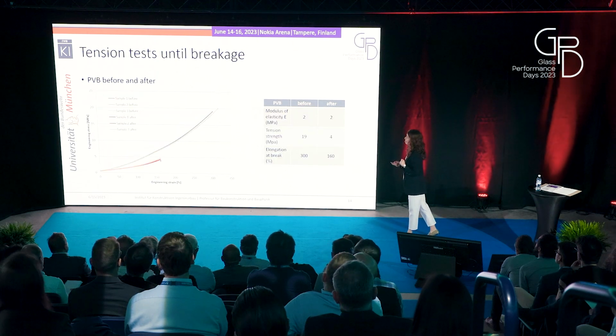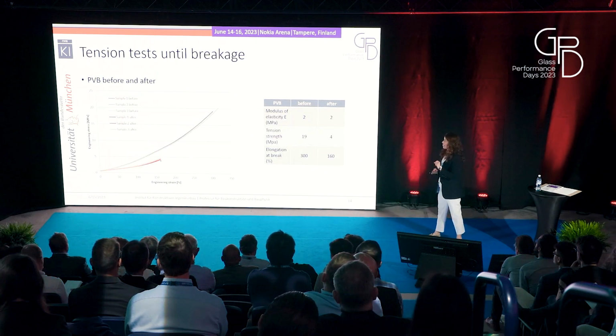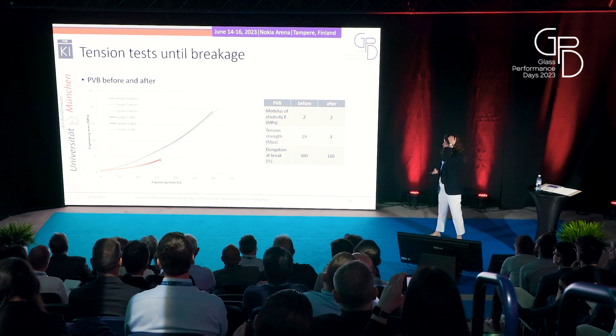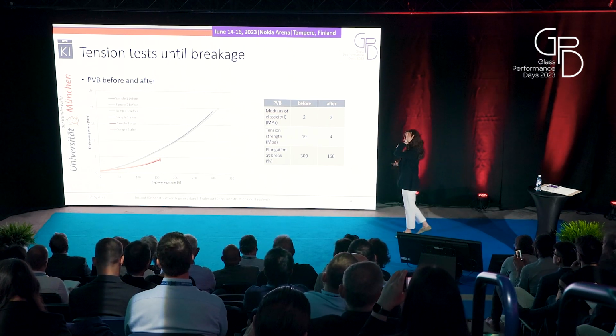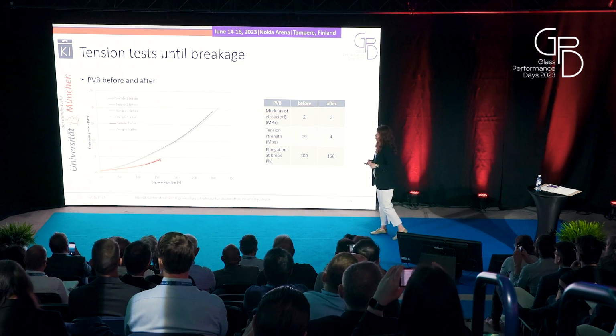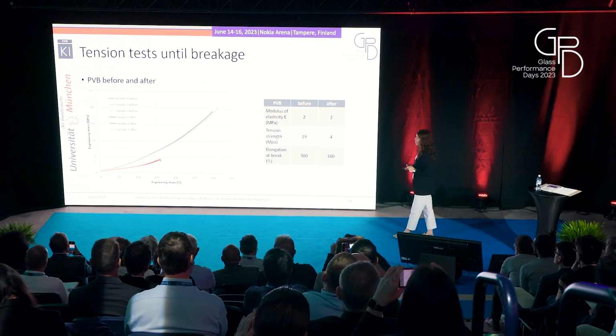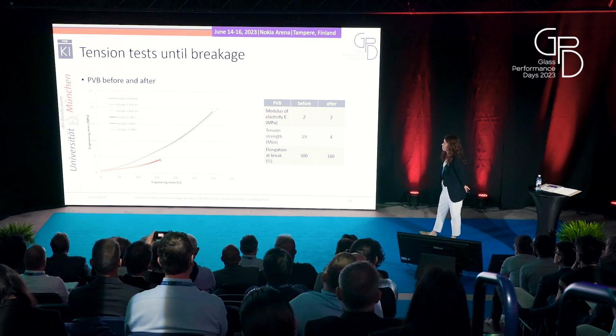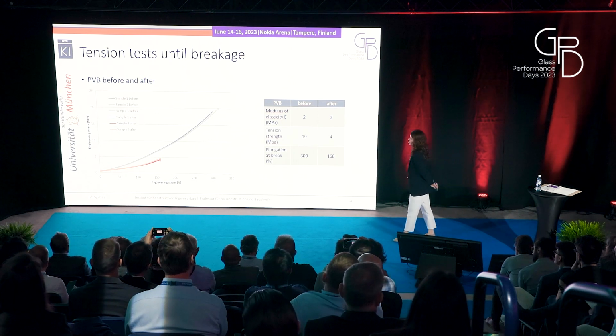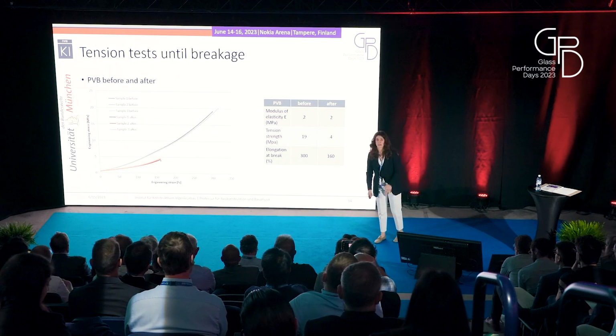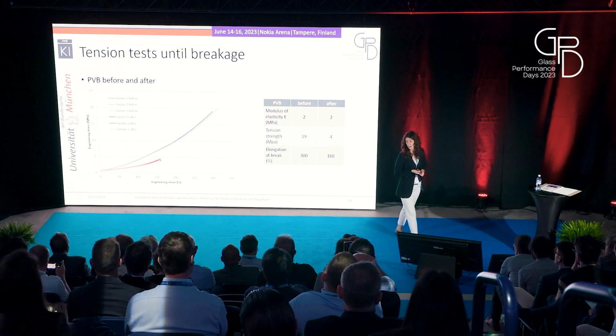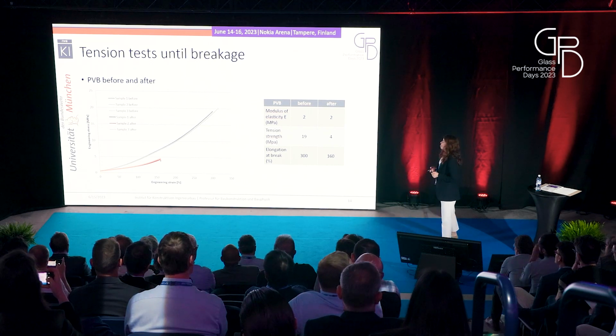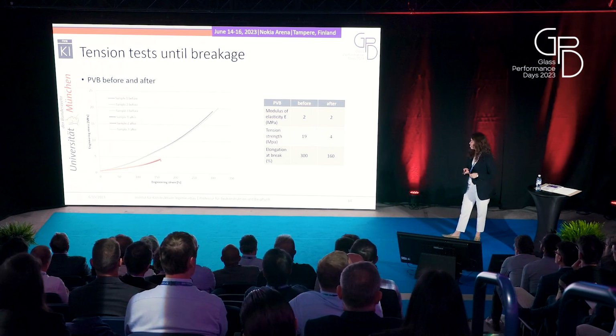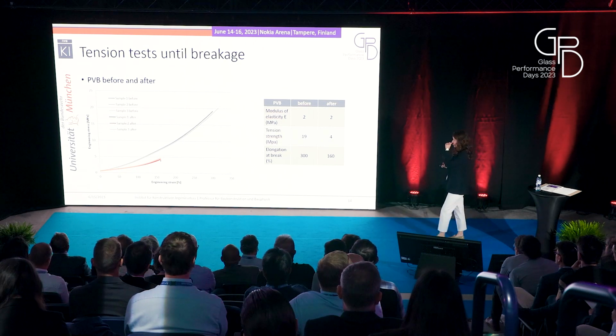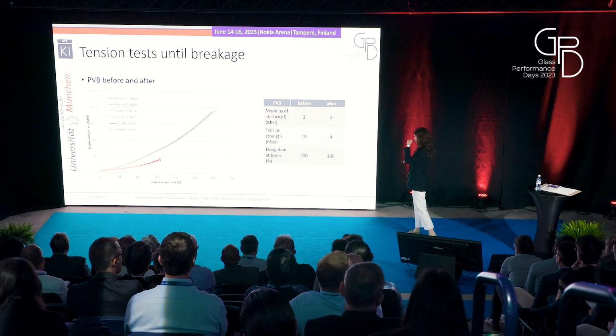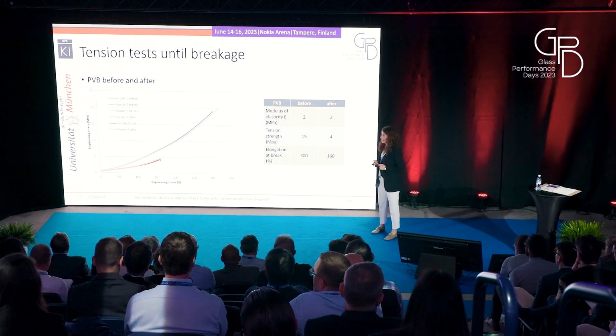And now here are the results of the PVB before and after. And just when we look at it, we can see that there is a difference. So again, gray results are samples before, and the orange ones are the samples after. So also in this first linear elastic part of the material, there's no huge influence. It remains mainly the same. But then the tension strength and elongation and breakage degradation actually happened.